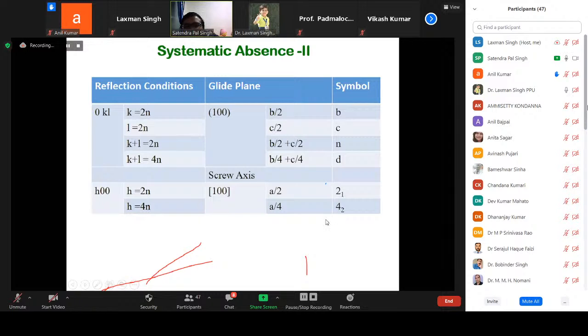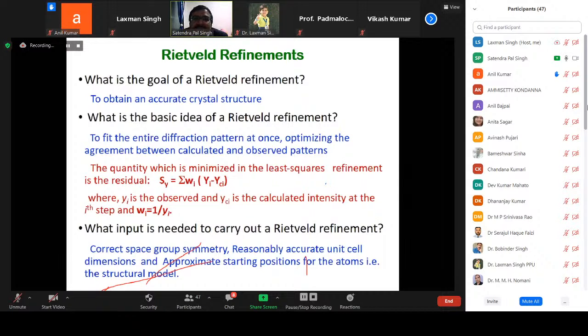So the systematic absences will give you information about the lattice centering and the various translation symmetries, like the presence or absence of a glide plane or screw axis. Once you know this, you can compare the given information, the lattice centering, the lattice symbol, the lattice parameters and the crystal system, from the space group table available in the International Tables for Crystallography. So what do you do after that?